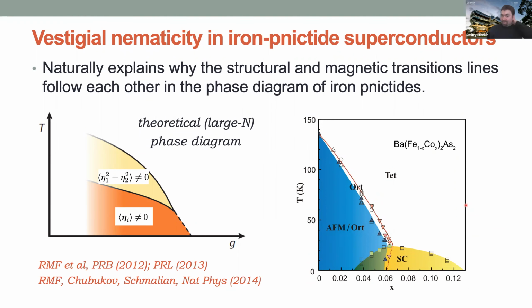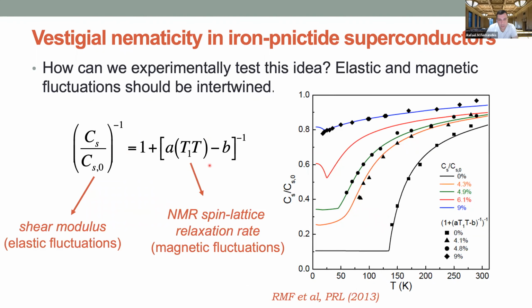Yes, thank you. Now, I just mentioned that with this formalism, you can go beyond and you can actually derive a general relationship between the elastic fluctuations and the magnetic fluctuations. The elastic fluctuations come from the nematic, which come from the magnetic. So you can derive this scaling between the shear modulus and T1T, which is the NMR spin lattice relaxation rate.